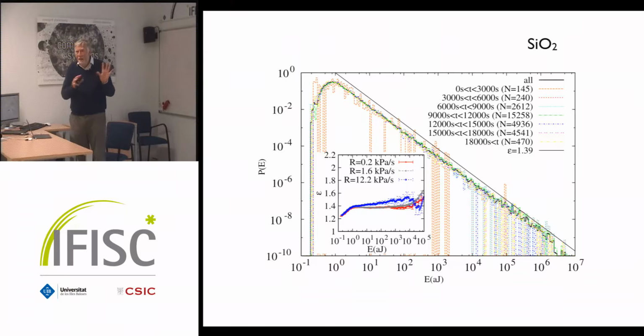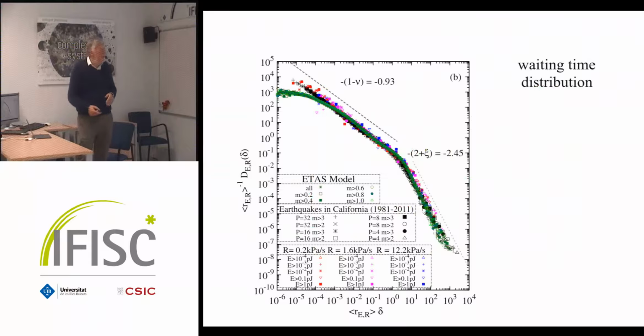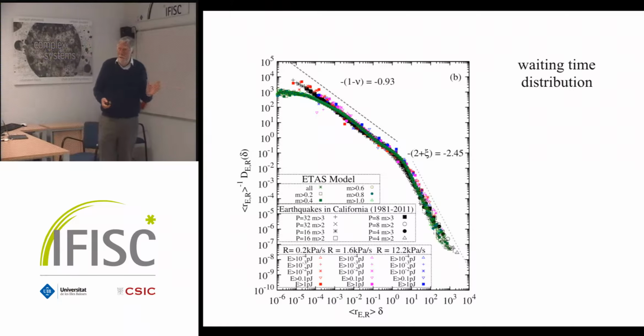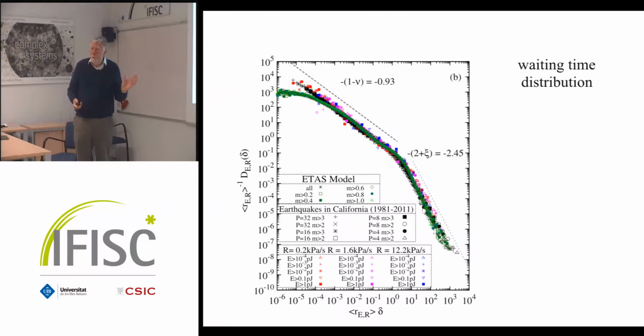So we have very, very good data, large data sets. And if you can work with these large data sets, you get fantastic data. Then you measure the time interval between 2 of these avalanches, and then you get, again, this one is the theory, and it fits the theory perfectly well. But what's more important here is, for fun, we have also plotted the same distribution for Californian earthquakes on the same scale. I mean, we have such a large scale. Why not add a few, 5 or 6 orders of magnitude?